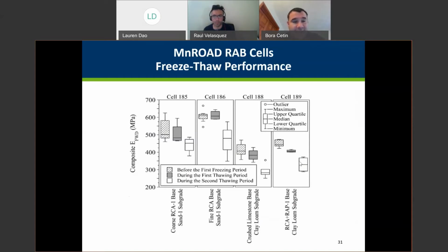When we look at how they perform during the freezing and thawing cycle, both in the first thawing and second thawing periods, again, coarse RCA and fine RCA materials outperform the limestone and RCA-RAP. And if you compare the RCA-RAP, after the first 2 freeze thaw cycles, the first cycle and the second thawing period, RCA-RAP also provides superior performance in terms of elastic modulus to crushed limestone base.